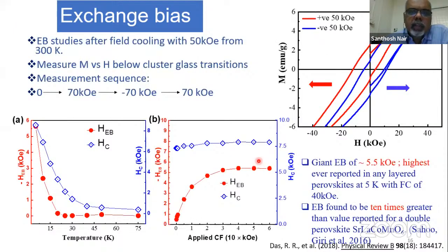That's what we investigated, and we see a fairly large exchange bias, something to the tune of more than 5 kilo-oersted, probably the largest reported at that stage on a layered oxide. And you can see the exchange bias with respect to temperature exists only below the glassy transition of 40 Kelvin. Above that, there is no exchange bias. And depending on the cooling field, at higher cooling field, it kind of saturates. It's pretty well known. To confirm it's not an artifact, we have done both positive and negative cooling fields, and the exchange bias shifts to the opposite sides, which confirms it's a real effect.